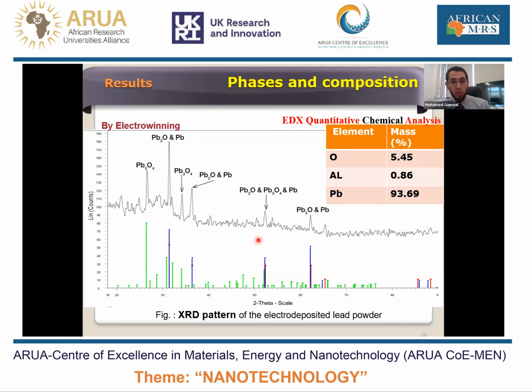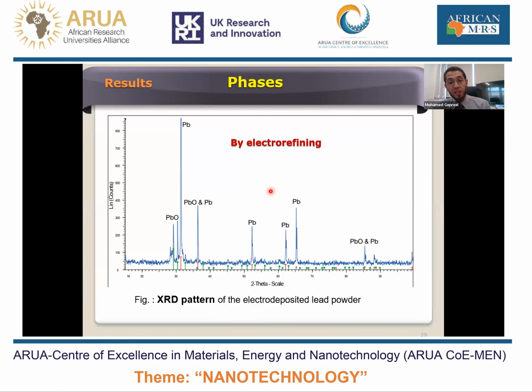Sometimes, depending on the production process, it is lead as core and lead oxide as shell. So the XRD shows us that it is a mixture of lead oxide with different levels of oxidation. We'll have a combination of an oxide core or lead metal core in the particle and a shell of different levels of lead oxides and so on. And depending on the techniques, we can manipulate this percentage or ratio of lead and lead oxide.